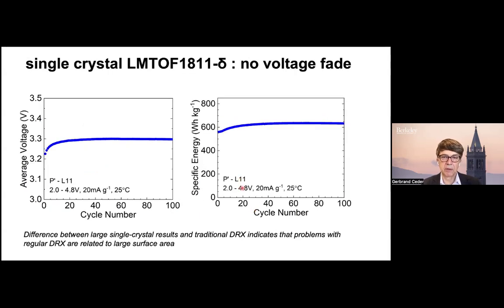Unlike other lithium excess materials, there is no voltage fade at all. Again, in the remnants of the formation, the voltage creeps up and then is extremely stable. Average voltage is about 3.3 volt.